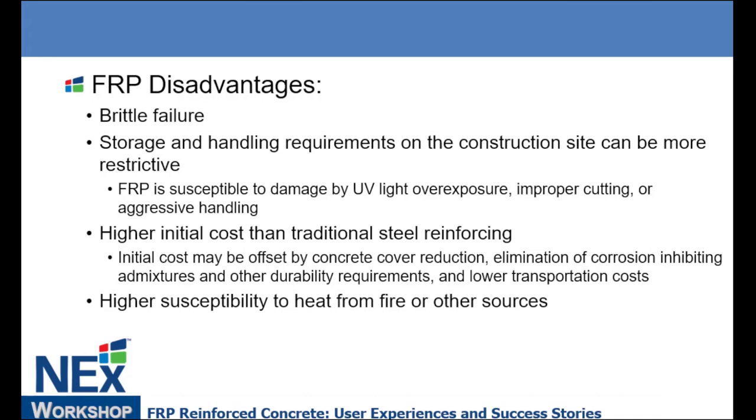And then we took that half inch of concrete savings and we credited that to the FRP. We also, especially in the long span garage, because that's in a location where chloride loading is very heavy, decided that if we used FRP, we could eliminate the use of calcium nitrite admixtures. So calcium nitrites are commonly used in areas of heavy chloride loading to increase the passivating layer around the steel. By using a calcium nitrite, you can essentially raise the corrosion threshold.